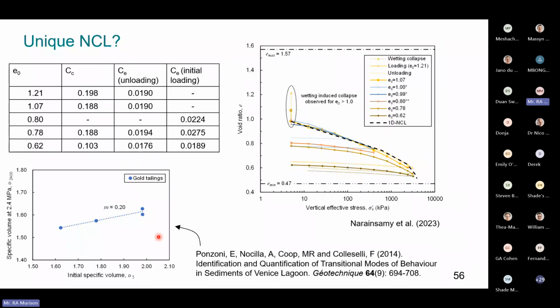So from this research group specifically, they have a few studies. The first recorded an M value of, I think, 0.14, and they considered this to be evidence of a unique normal consolidation line. An M value of around 0.4 was said to be uncertain or inconclusive, whether it was clay-like or sand-like behavior, and an M value of close to 0.7, they said was evidence of sand-like behavior, parallel normal consolidation lines. So given all of that and our low M value of 0.2, it's probably fair to say that the behavior we're looking at here complies better with clay-like behavior with the unique normal consolidation line than sand-like behavior that we saw.